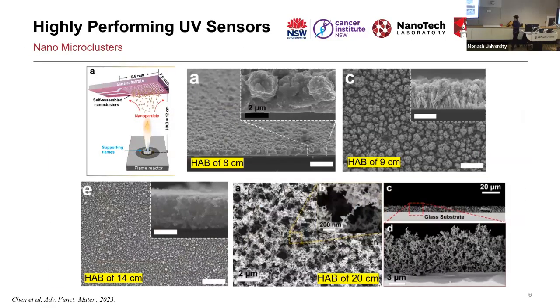So I'm going to present very recent work since 2023. I don't want to go very far back. One of the good things about this machine is that we can change a lot of parameters. One of the parameters is the height above the burner. We can simply put the substrate closer to the fire or very far from the fire. Just by changing the height above the burner, we can change the structure significantly. You can see at 8 centimeter, that is the type of structure, of course, a little bit tilted. What you see over there is a bit tilted substrate and also the film. 9 centimeter is a bit more porous. You go to 14 centimeter, you can see how fluffy the structure will be. And if you go for 20 centimeter above the fire, then the structure will be extremely porous.